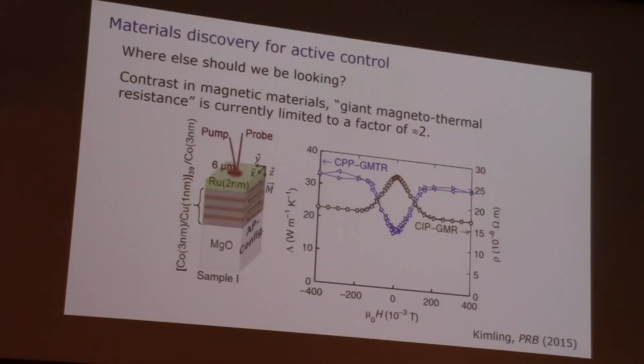All right. Here's something that's extremely fast. This is a ferromagnetic system. It's what we would call a synthetic antiferromagnet. It's made from layers of cobalt separated with spacers of copper. You can see the spacing. This is true nanoscale, 3 nanometer, 1 nanometer. Stack it up many times, 39 times, make this multilayer. What happens is that the magnetic order of the cobalt layers is anti-parallel in zero field, and at a very modest field, a couple hundred Gauss, then the